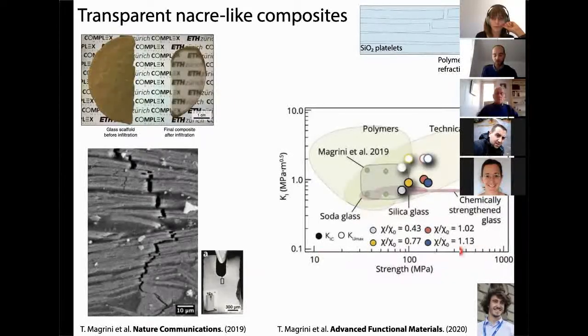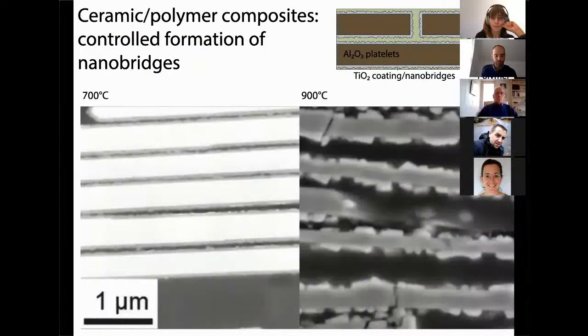So if we look at the strength versus toughness of these materials again, we ended up with something that is quite as strong and even a bit stronger than normal glass, but also a lot tougher compared to other transparent materials. Right, so we've looked at the interface in terms of polymer: the tougher the better.